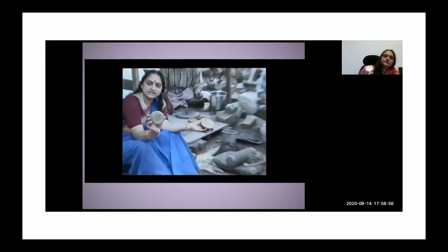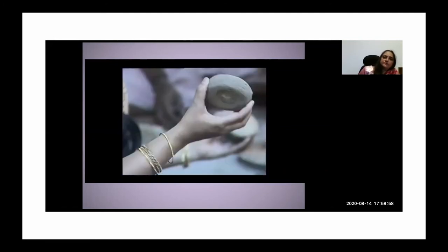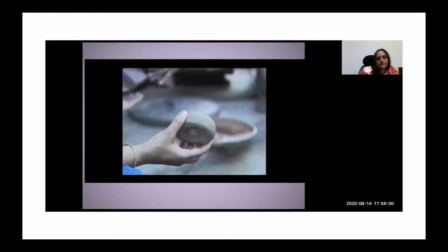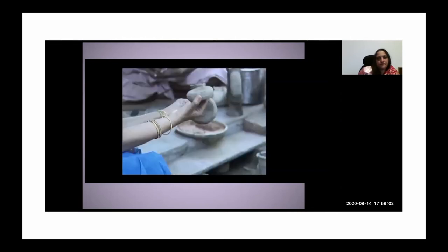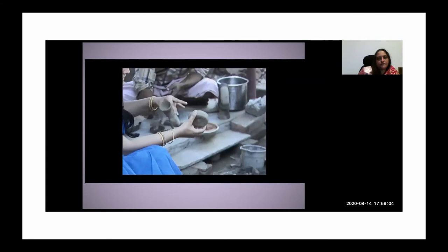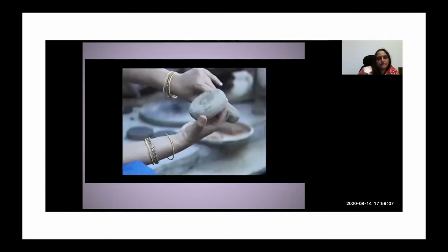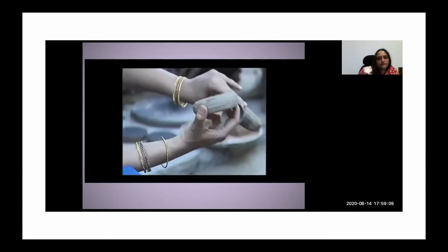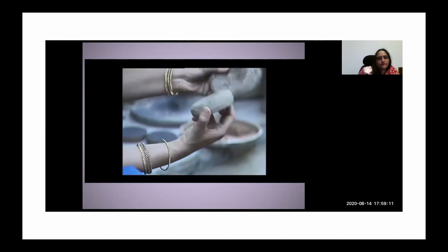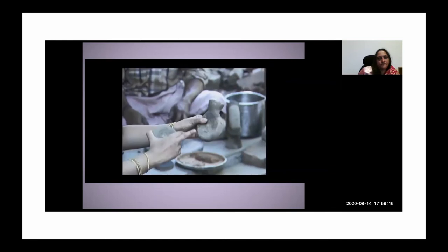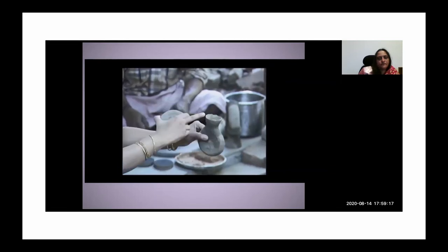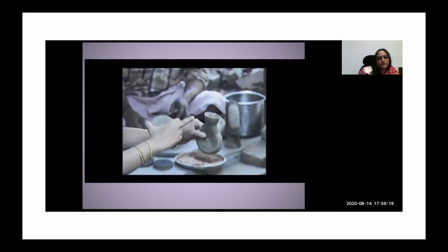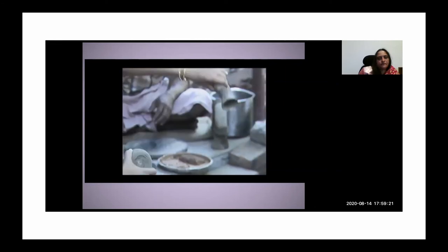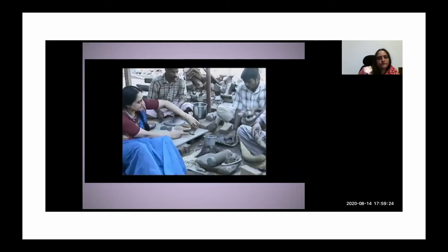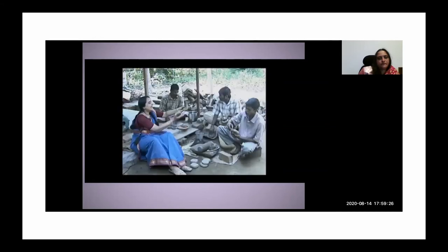And then on this encased clay mold, they make a little channel, a wax channel. And then this is the mouth here. This forms both a crucible and a mold. The top part is the crucible cup, and this is the mold. So then they will put the metal to be cast here with a channel connecting it and cover it. And then they will heat it in the reverse process so that the metal gets molten. They will tip it over so that it forms the blank.